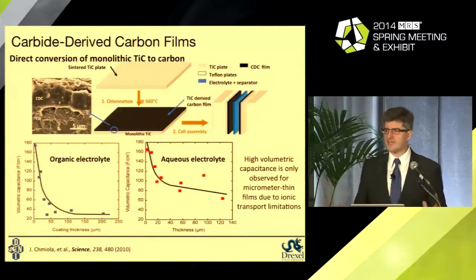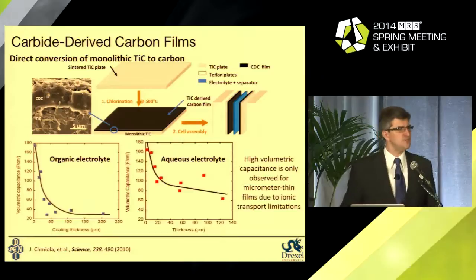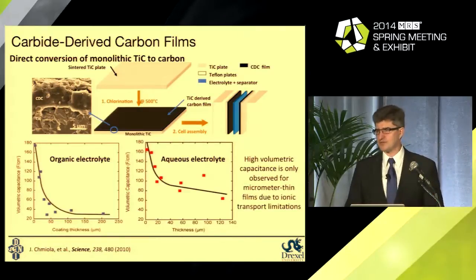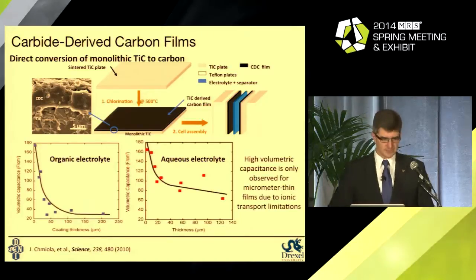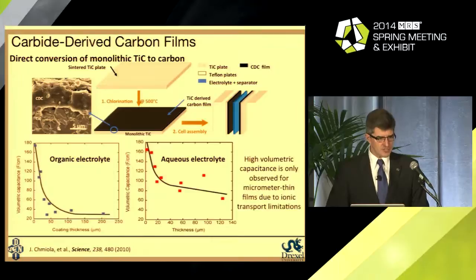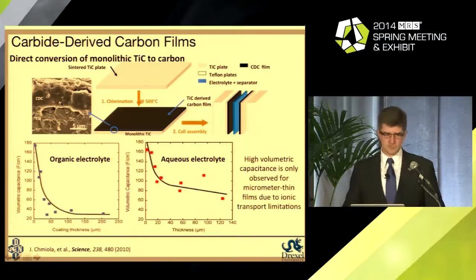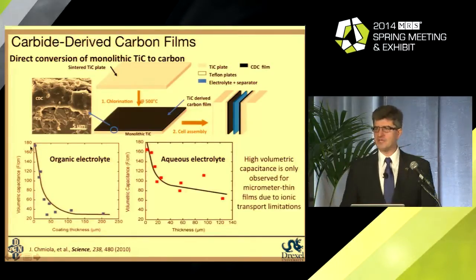And at a certain point, we were very happy with our finding and our knowledge. We knew how to make the best supercapacitor material here. Everything is simple. We take plates of materials, 100, 200 microns thick, with no mesopores, no macroporosity, with just micropores tuned to the size of ions, and we will make the best electrical energy storage device ever. And of course, we produce these plates. We make carbide-derived carbon films ranging from microns to a couple of hundred microns by transforming, for example, titanium carbide into CDC. And we actually got wonderful performance, 100 farad per cubic centimeter, 3 times that of a commercial supercapacitor.